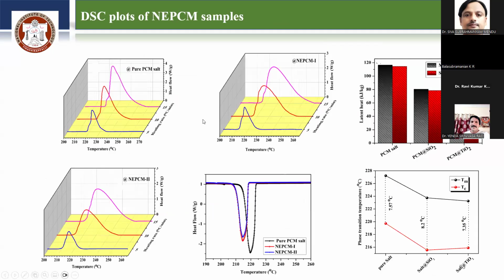Next is the differential scanning calorimetry, at different heating rates. In the DSC we can see how the variation is obtained for pure PCM salt, NePCM salt and NePCM 2 salt also. The next figure shows the melting and solidification for PCM salt. You can see the melting is happening quickly for SiO2. However, the time for melting as well as solidification is further reduced for TiO2.